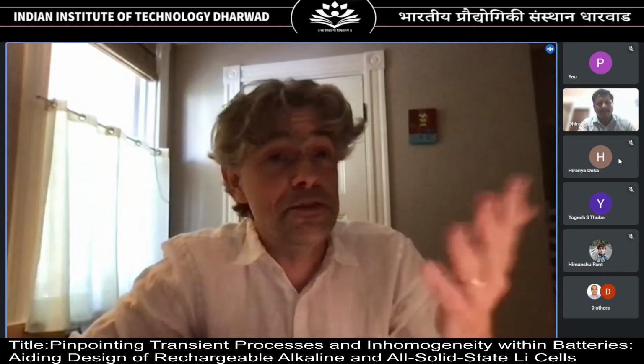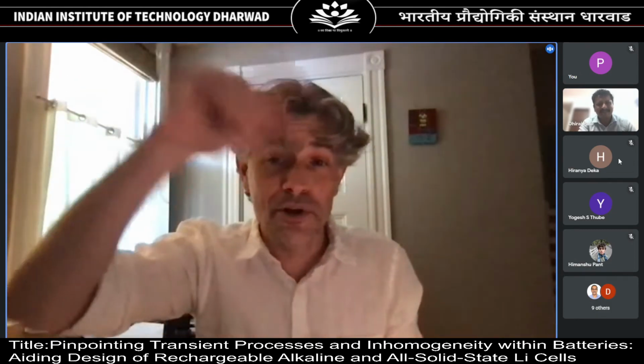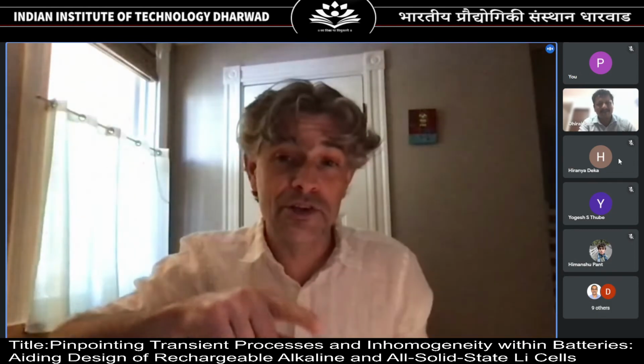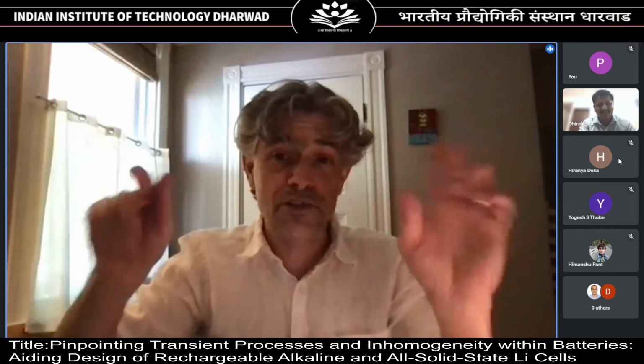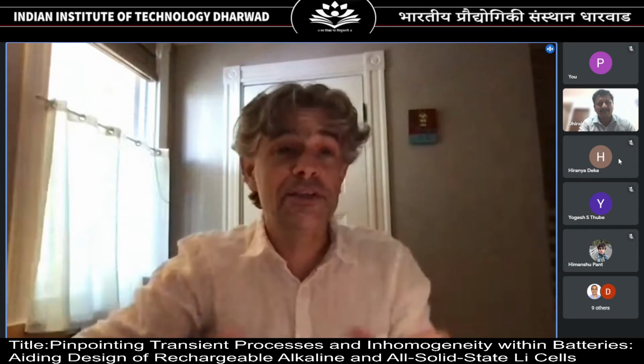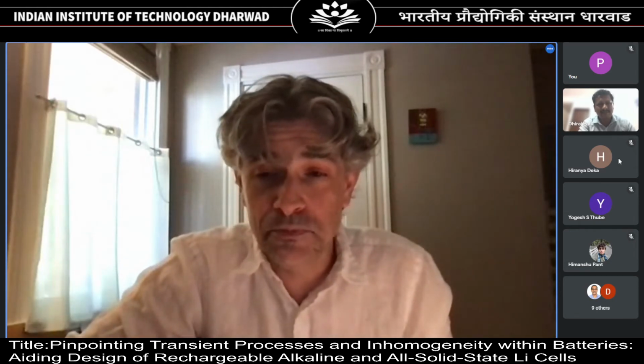So growing lithium dendrites, anywhere the lithium dendrite grows, you have the Butler-Volmer equation happening, and that interface is moving. And then if it branches, it'll be happening in all those places. And so people usually try to simplify that equation.